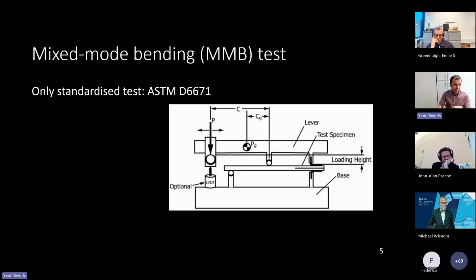If we move to mixed mode bending, then the most common test is the MMB or mixed mode bending test. This is also the only test today that we will cover that is standardized, in ASTM D6671. You can see it illustrated here. It's essentially a double cantilever beam with a bit of a twist on it, with a sort of end notch flexure type of loading. And by controlling the lever that you have here, moving it left or right, you can also change the mode mixity and study a wide range of mode 1 to mode 2 ratios.